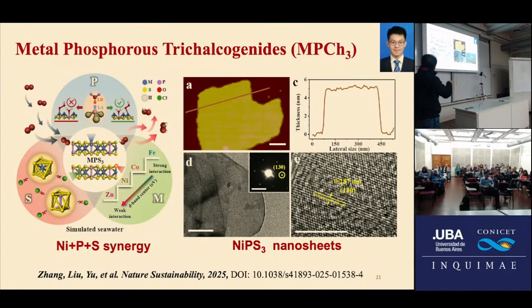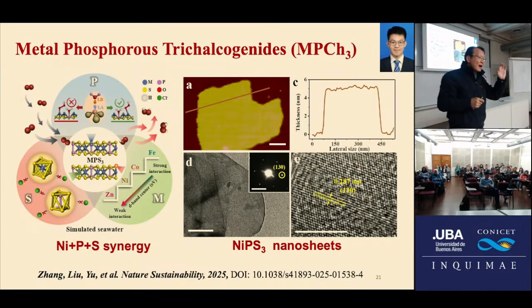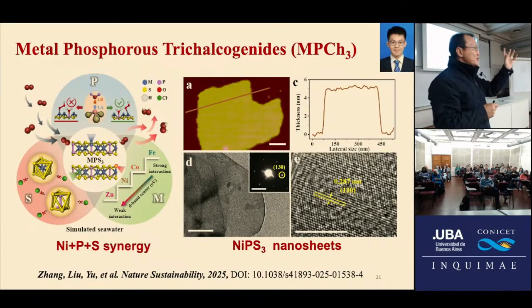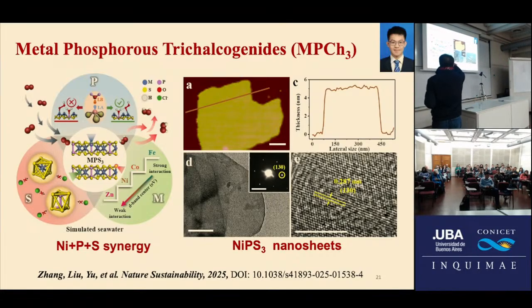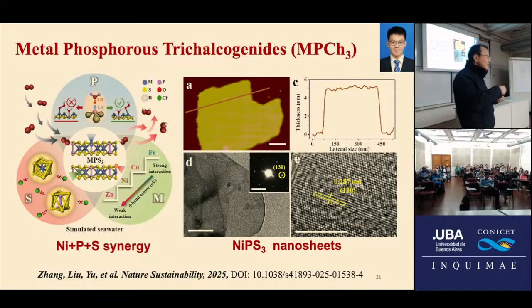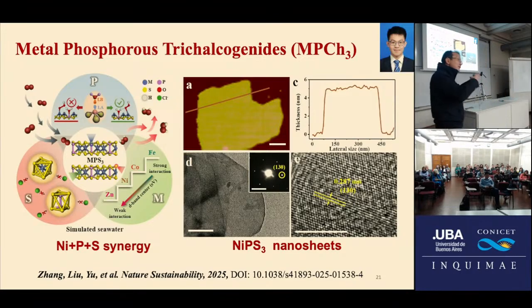Maybe I just use this slide to tell you. So what's the contribution of the sulfur? Six sulfur atoms can form an octahedral cage, and the sulfur has a negative charge. So both the metal and the phosphorus are hidden inside this negatively charged cage. This provides the intrinsic repulsion towards the chloride. As Shi-Zhang mentioned, in his case it is hydroxide that repels the chloride, while in this case it is a molecular structure, the octahedral sulfur cage, that does this job.